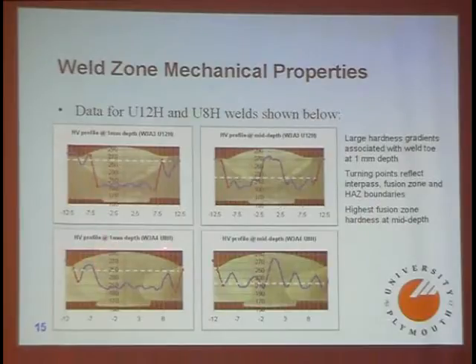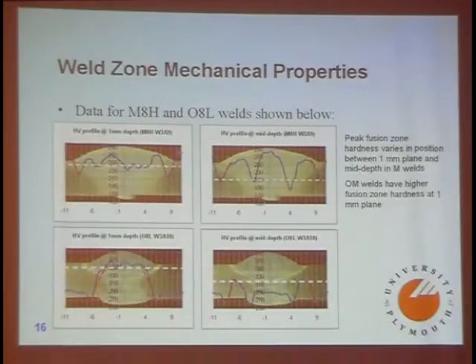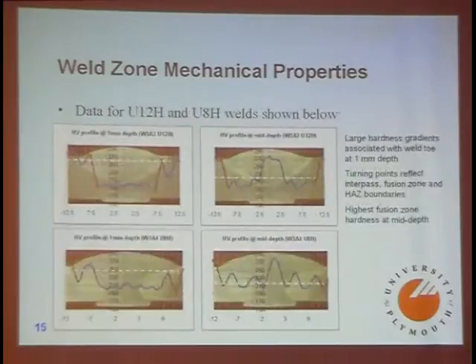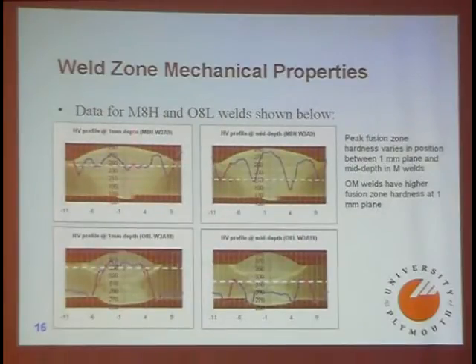And this just shows you a different one. This is undermatched 8H, high input, at, again, 1 millimeter mid-depth. And the turning points you can relate fairly well to interpass, fusion zone, and heat affected zone boundaries. And just to indicate that there are substantial differences, this is typical data for a matched 8H, which is those two there, and an overmatched 8L, which is that data there. So there are big differences.